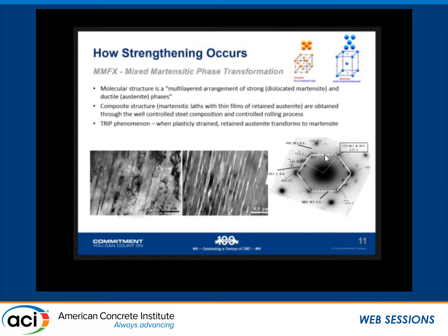The thick bands are martensite and the thin bands are austenite. They're retained austenite. Then when you tensile test the steel, the austenite will turn to martensite before it fails. So you get phenomenal strengthening from this type of a reaction.